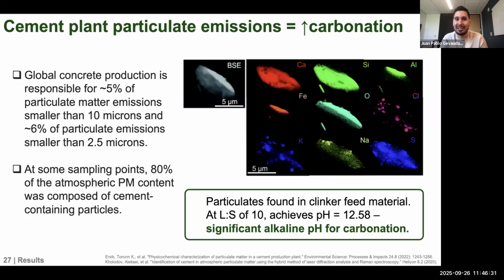What we have seen from research is that, particularly for the particulate emissions from cement manufacturing, 80% of those particulates are cement-containing particles. And you can see here in this SEM image with the spectroscopic map that these are essentially cement particles that are really, really fine. So what we see here is a problem, but also an opportunity. Because when we tested these particulate emissions from a cement plant, we saw that even at a liquid to solid ratio of 10, we can achieve a really high pH of 12.58, a significant alkaline pH for carbonation.